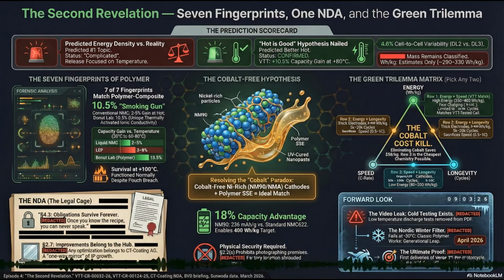Exactly. And if we look at the other predictions we actually nailed, we predicted the cell would perform significantly better hot. The new data confirms that spectacularly, showing a 10.5% capacity increase at 80 degrees Celsius. Huge jump. It is. We also predicted that if multiple cells were tested across these reports, we would see cell-to-cell variability, and we did. The DL2 cell from this report has a roughly 4.6% capacity gap compared to the DL3 cell from the first report.